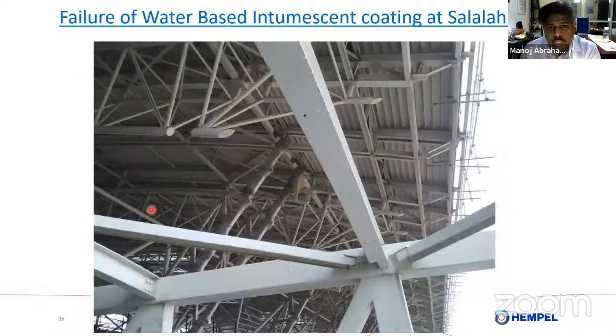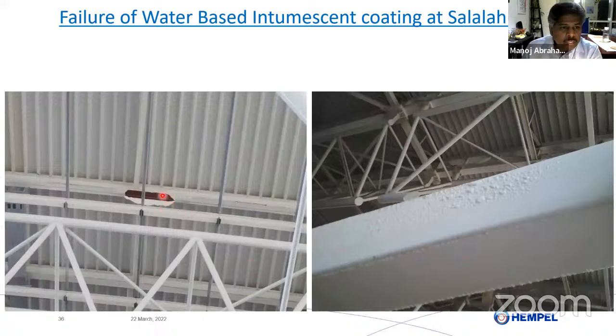Another example, which is closer to home. This is in Oman, Salalah Airport. A lot of people say, we applied water-based and then we put a top coat. Not one, but two top coats we applied. It should protect the intumescent underneath. No, it does not protect. You see this? The intumescent is peeling off. And you can see these bubbles coming out, and these are basically on the top coat. You can see that this is a gray top coat, and you can still see a lot of bubbles coming in.